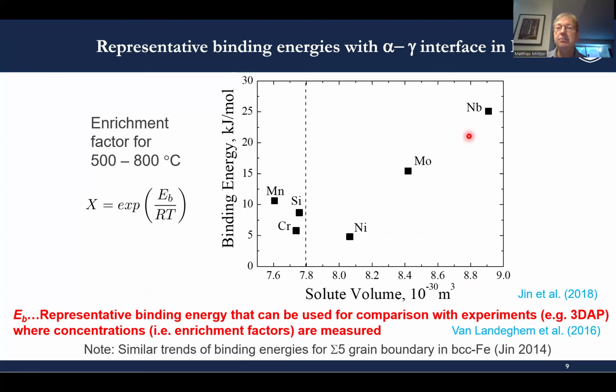And then we see niobium and also molybdenum tower upwards here in the right-hand area as much larger solutes, which promotes their segregation to interfaces where there's excess volume. So it reduces the misfit that these atoms see in the bulk lattice. And then we have atoms with similar size to iron, like manganese, silicon, chromium, and they still have an appreciable binding energy, and we'll have to make different considerations for these elements.